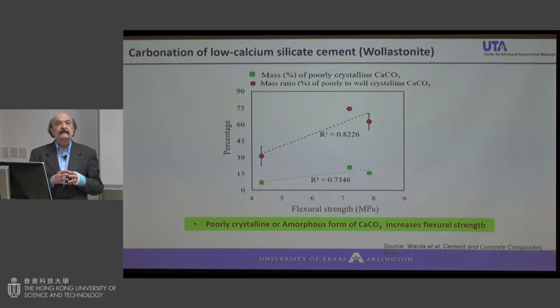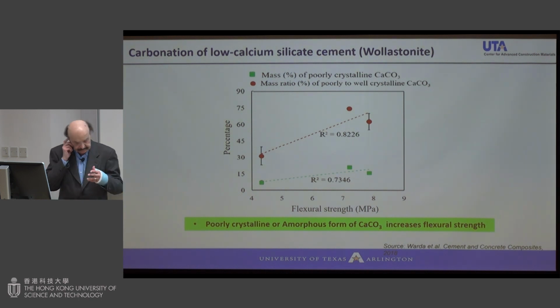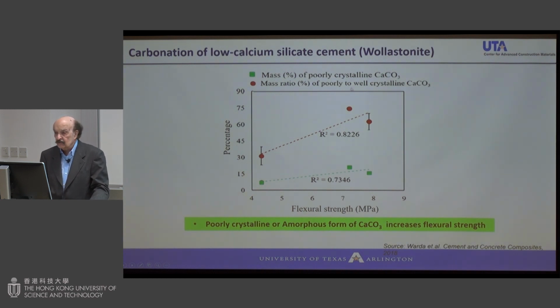So I mentioned that Warda Ashraf, my colleague at UTA, is manipulating this by adding, for example, dopamine. So you have amorphous calcium carbonate. If you look at it, here is the flexural strength, and what is plotted here is the ratio of how much poorly crystalline calcium carbonate there is versus well crystalline, such as calcite, versus flexural strength. So you can see that the more amorphous material you have, if you can stabilize it, you can increase strength. So that's one direction where innovations are being done.